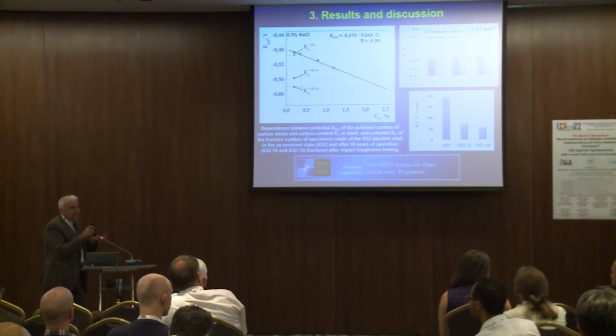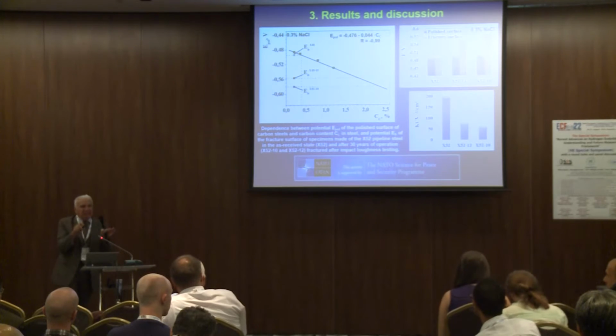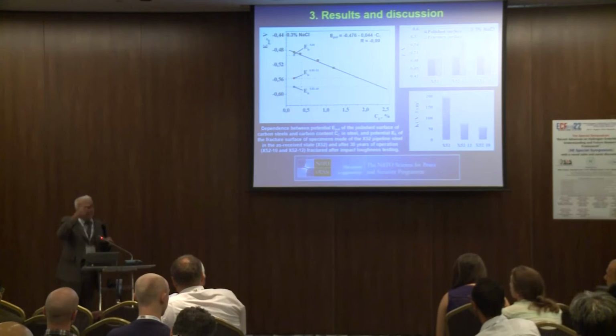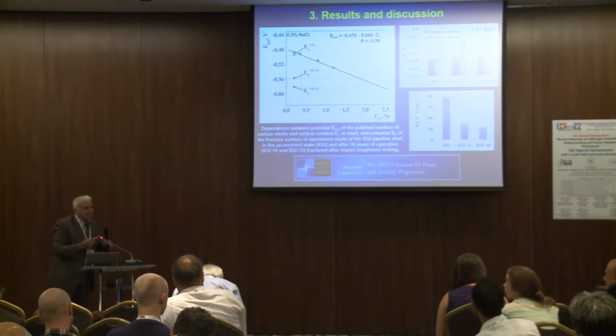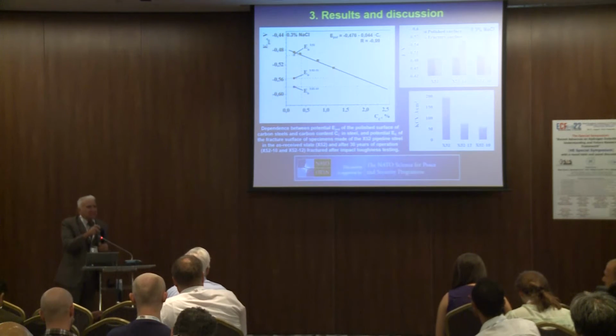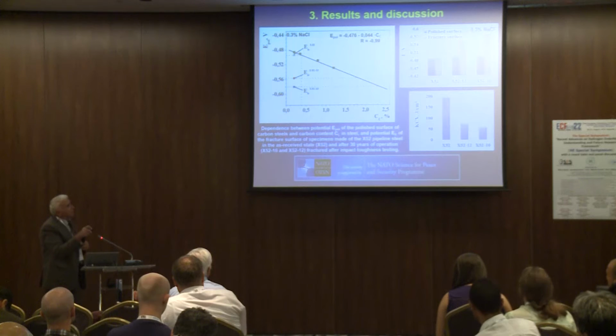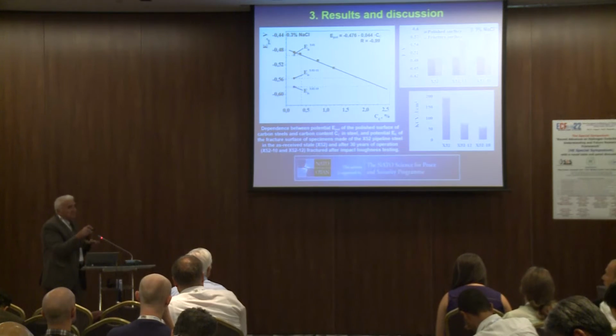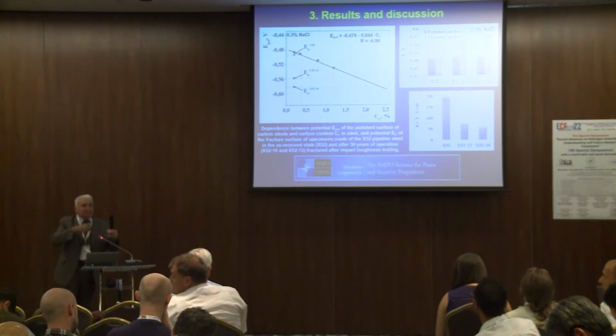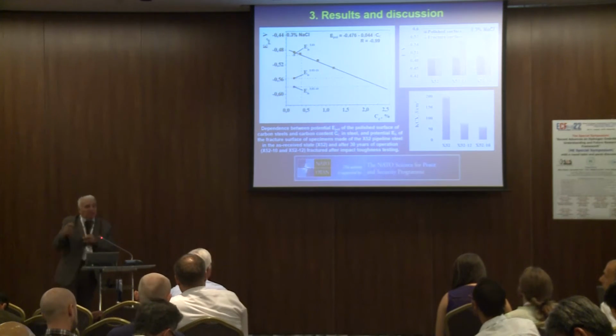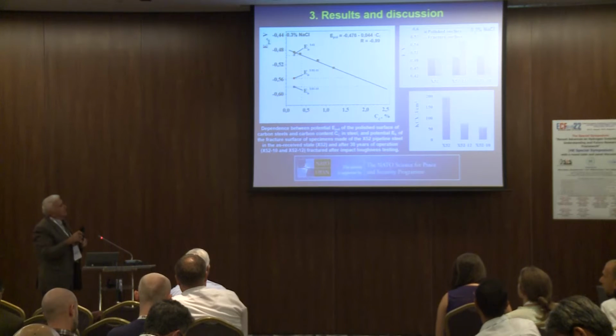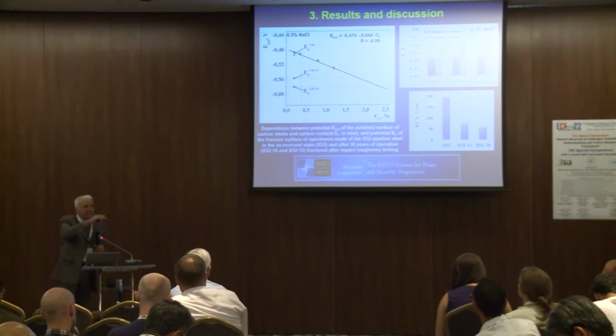It is very important to show that for the as-received state, the difference between potentials is small. It means that a fracture surface with greatly deformed material, ductile behavior in such a case, does not have so strong an effect on potential as for aged materials. For aged materials, the level of plastic deformation is less. The effect of plastic deformation on the potential shift is, in our opinion, negligible in comparison with the effect of the change of state of materials.